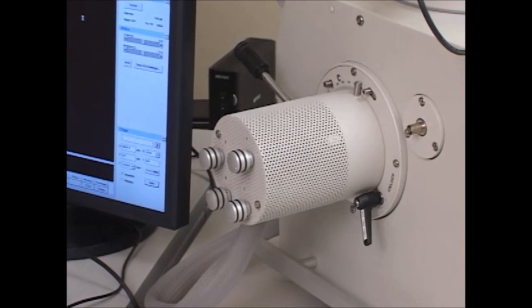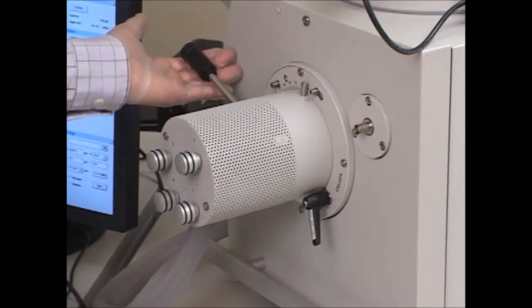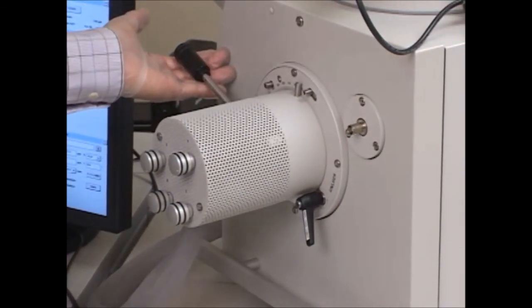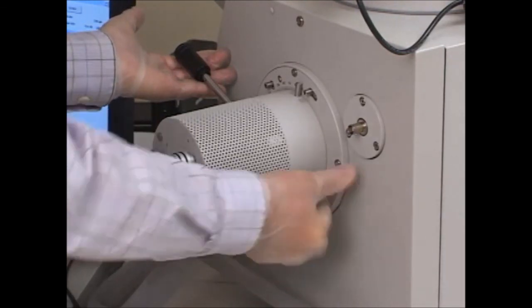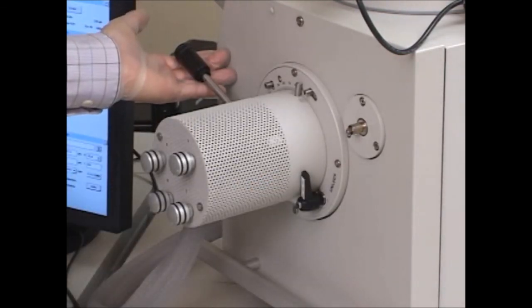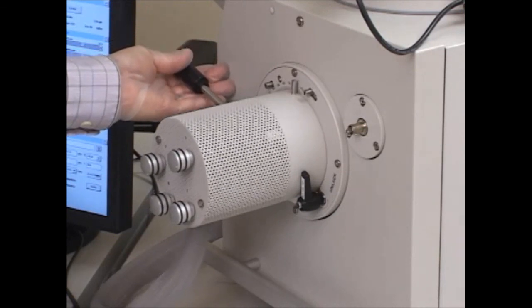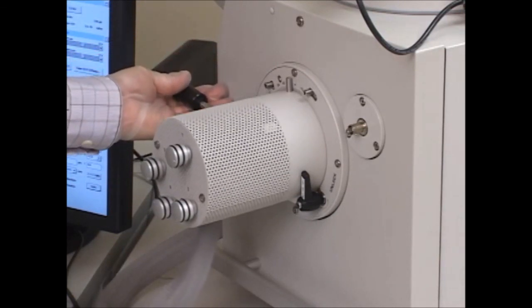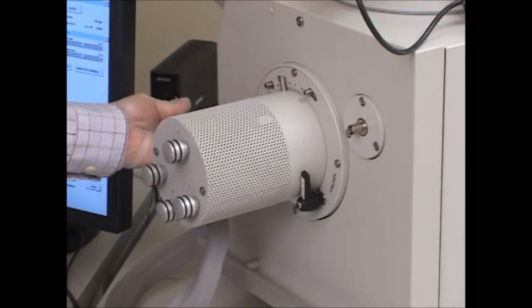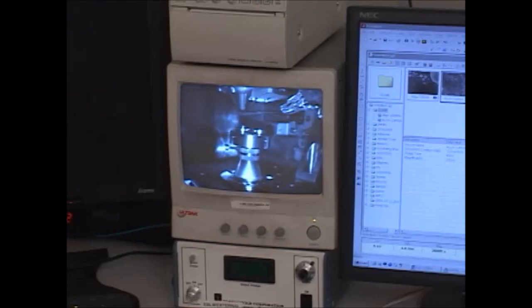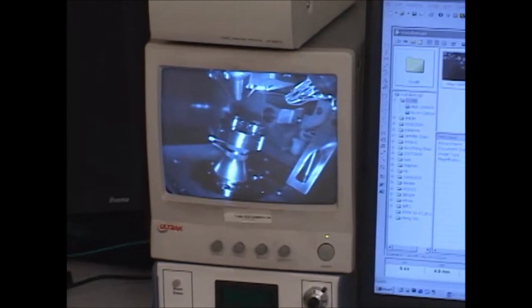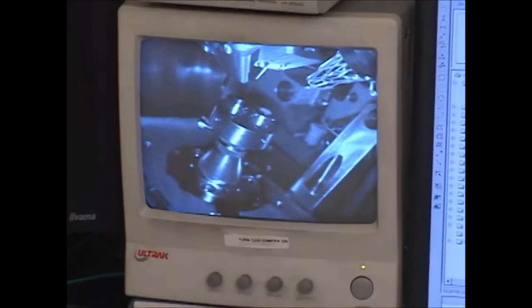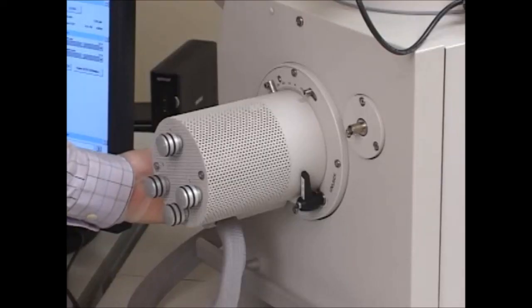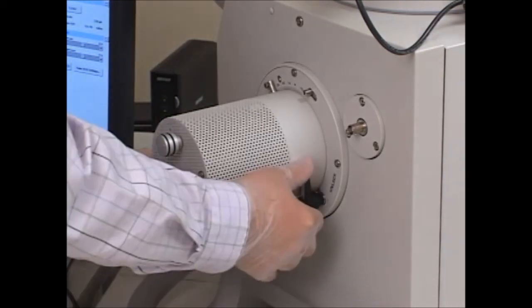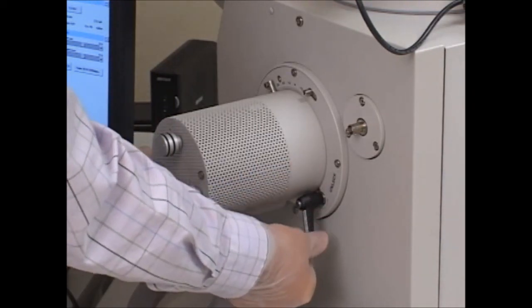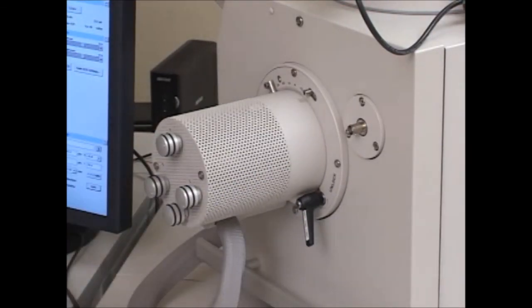And to adjust the tilt, we just want to support the weight of the stage with our hand here and unlock the stage screw, and that frees it up for rotation. So I can tilt the sample down up to 45 degrees in this direction. While I'm doing that, I want to be watching the CCD camera to make sure there's still clearance over there. And then when I've gotten it tilted to the angle I want, I just reset the stage lock and it'll hold that angle.